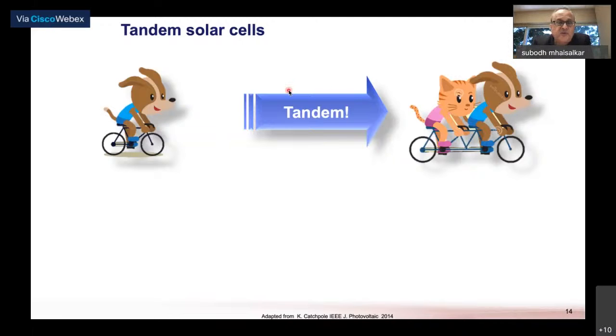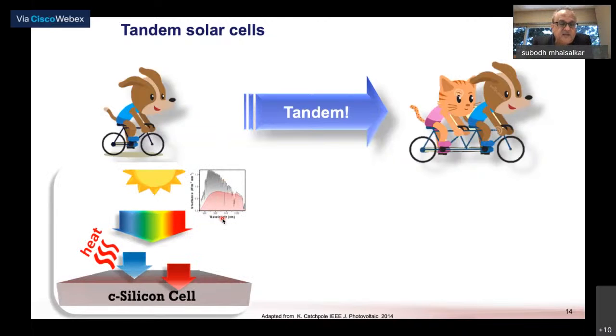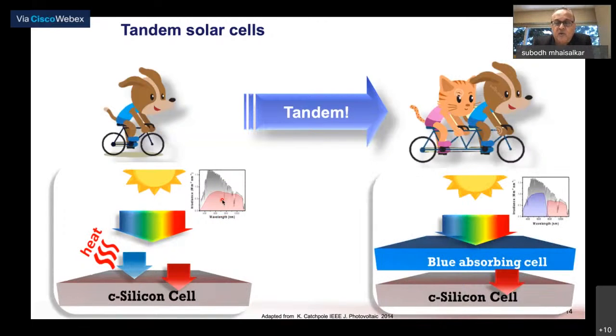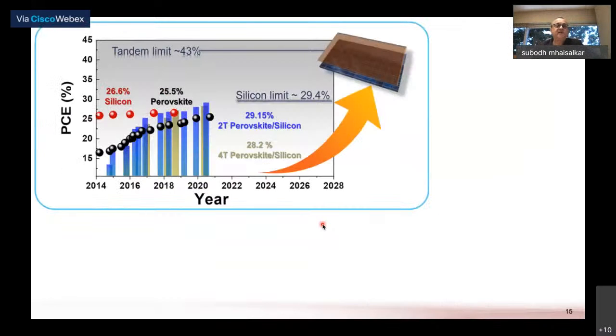The approach that I'm going to focus on today is going to be that of tandem solar cells. And in this concept, one would couple the possibility of multiple absorbers working in tandem with each other. So the possibility of a blue absorbing perovskite that can be coupled with the output of a silicon solar cell is extremely appealing, because as I'll show you, this really gives the possibility of surpassing the silicon solar cell limit. The limit of silicon solar cells more or less is acknowledged to be in the range of 29.4%. The theoretical limit of perovskite silicon tandems, however, can be as high as 43%.